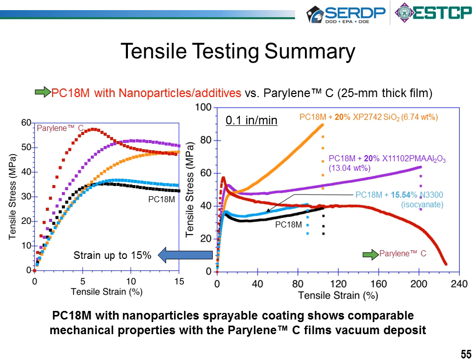But more importantly, because it's vacuum deposited, it has a fairly significant masking cost because all the masking needs to be vapor tight, vacuum tight. Otherwise, you get inadvertent coverage of your electrical contacts on your connectors, which is bad. It also is difficult and not really practical to repair with Parylene. So most of the repairs on Parylene revert back to a polyurethane brush coat of some sort. So, you know, that's problematic. But with our 20% nanosilica formulation, we did get comparable properties. It was in the ballpark of the Parylene C, so we felt pretty good about that.